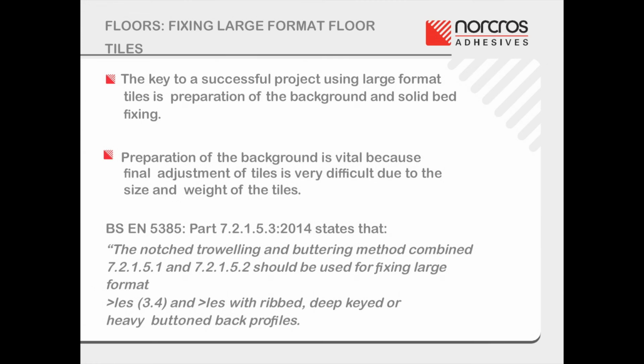Selection of a suitable adhesive is also paramount, and as stated in the TTA document Large Format Tiles in Internal Tiling, when fixing tiles to floors, a cement-based tile adhesive meeting the requirements of Category C2 conforming to BS EN 12004 should be used. A Class C1 adhesive may be suitable providing that the tile does not have very low water absorption characteristics, Class B1B or A1B and higher, and the floor is of solid construction. For fixing larger format tiles which have a greater surface area to cover with adhesive, bearing in mind the importance of achieving solid bed fixing on floors, use of a pourable lower viscosity adhesive would be advantageous.